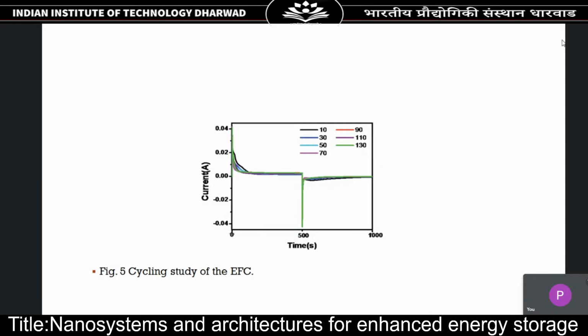And this is a cycling study, so we had carried out up to 130 cycles. You can see that there is very good fidelity of the behavior. There is not much fade of the charging or the discharging.